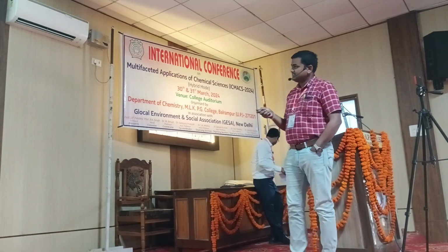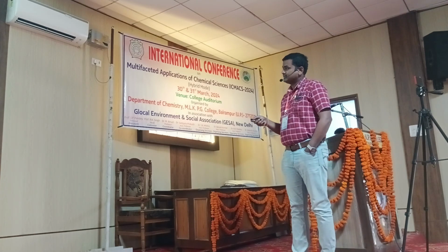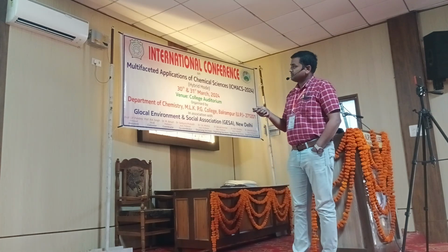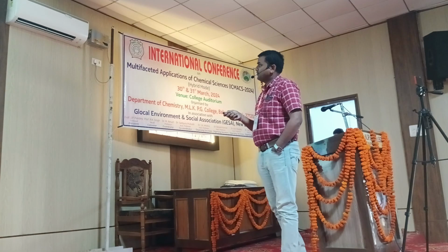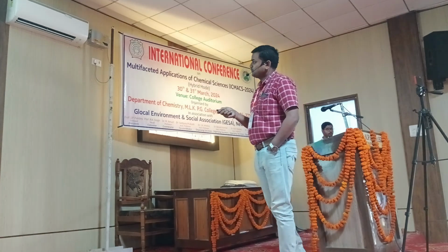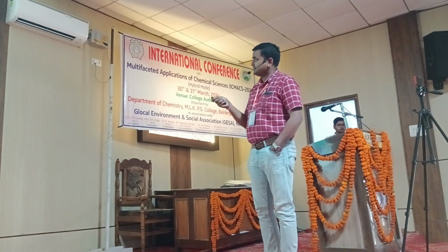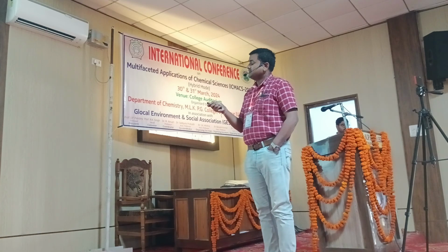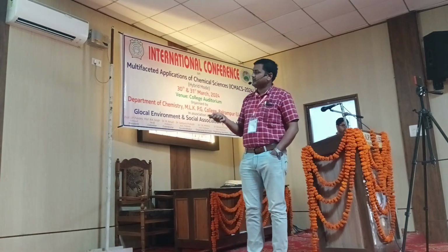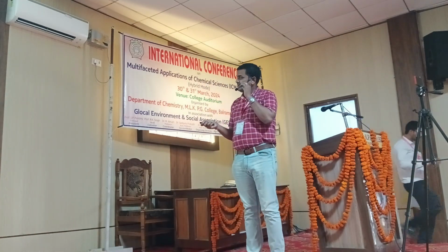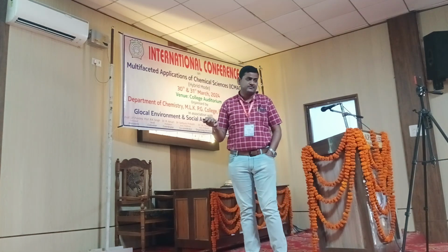We have also seen that by changing the graphene quantum dot concentration, there is a shift from blue to red, which is the J aggregation. At a graphene quantum dot concentration of 21 microgram per mL, we found the perfect white light coordinates, 0.28 and 0.33, with a color temperature of 8479 Kelvin. But as the concentration of graphene quantum dots changes from 1.3 microgram per mL to 168 microgram per mL, there is a shift in color coordinates from white to red because of J aggregation.